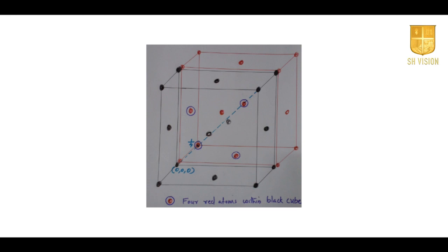If it is a silicon crystal, all are silicon atoms, or germanium atoms. So these lattice positions are chemically identical, but they are not equivalent, in the sense that we cannot move from one lattice position to another by the lattice translation operation. Therefore, they are considered as two independent separate lattice positions. That is how we get the diamond cubic crystal structure.